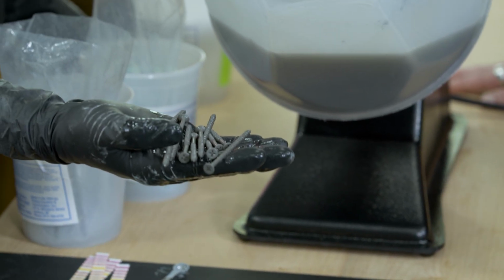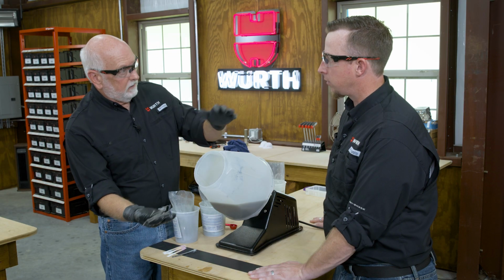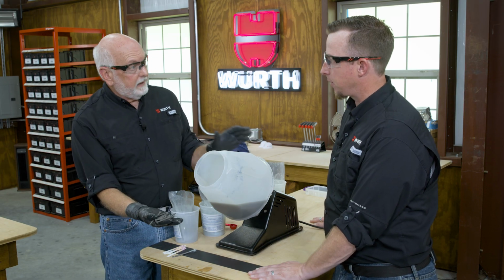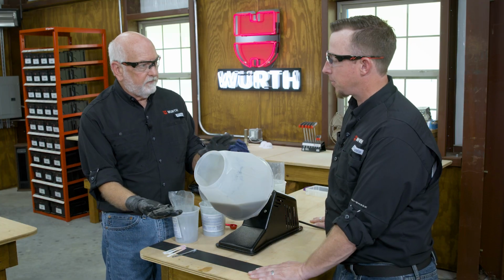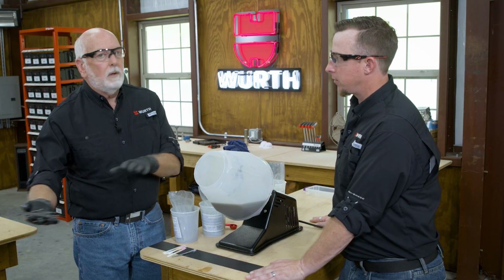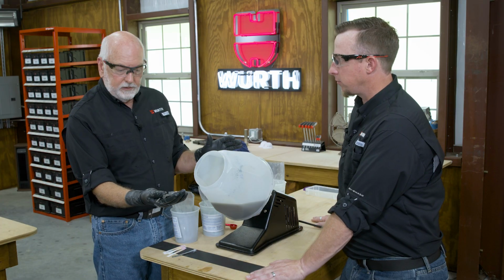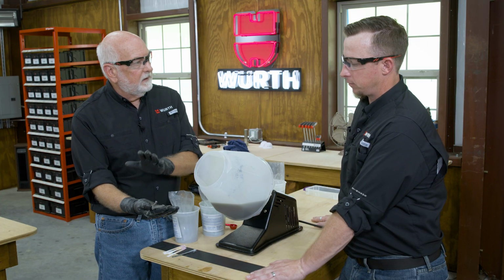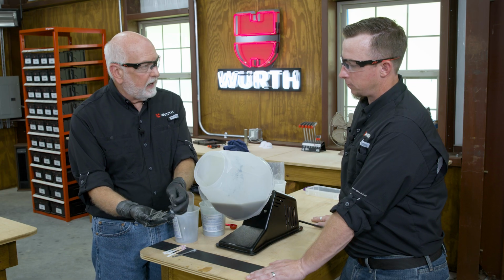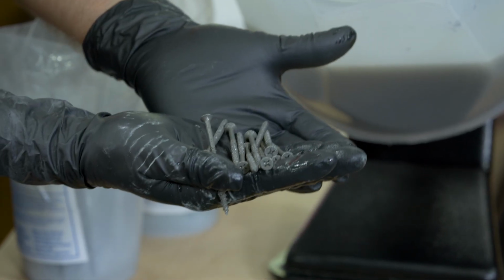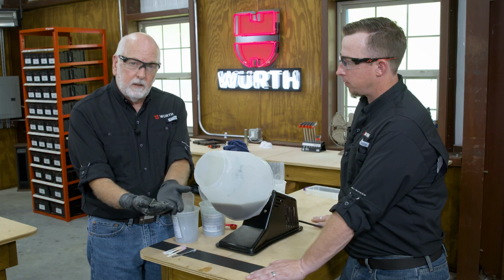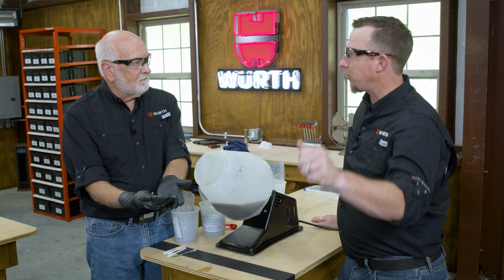Now, what happens in the process is that the entire barrel gets dumped out. Yep. It goes through magnetic separators so that the metal fasteners are separated out from the glass beads, and then it goes into a drying operation. Just an air dry. Yeah, just an air dry. And so now, as measured out properly, we have the right thickness of zinc put on here. These screws right here, I'd probably put anywhere from 5 to 12 microns. And this is fully evenly covered, you can see them. They go out and they're dried, and then from there, if you want a chromate, you put a chromate on there. If not, they go on into packaging and off they go. Out the door. Mechanical applied zinc.